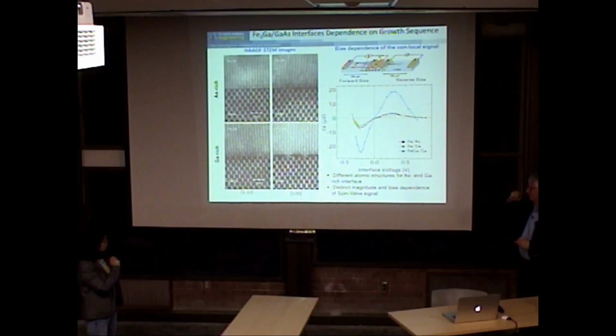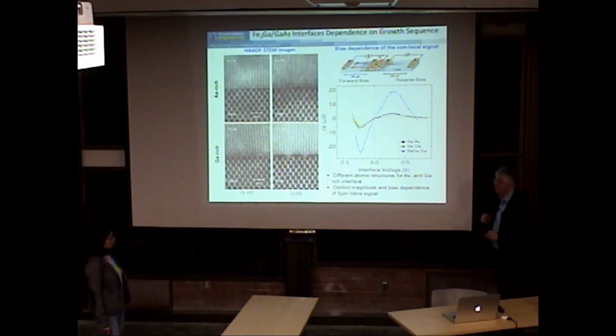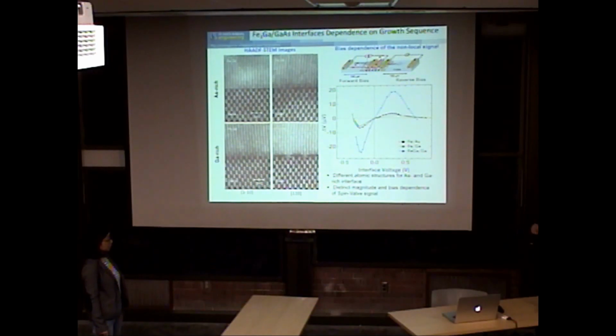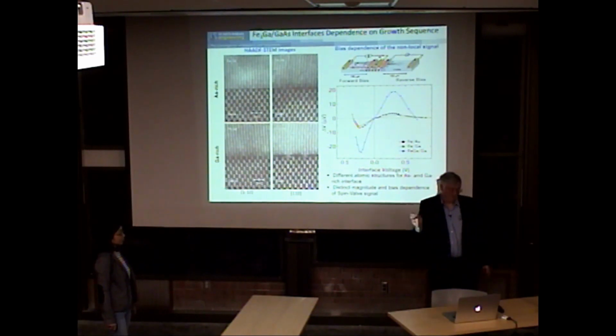For this material you compared arsenic and gallium-rich interfaces. Yes. But for the other material, the cobalt 2 manganese silicon, you didn't really mention it here. We tried the 4x4 surface of gallium arsenide only, and we do know it reacted. Because it worked, we said we're not going to go back and see if it's better with the gallium rich. That's the only reason we didn't do it. It was also a bit more tricky to get the gallium-rich surfaces to work, so we said, let's keep what's working. But I would be interested to go back and see if we can go even higher with a gallium-rich surface.